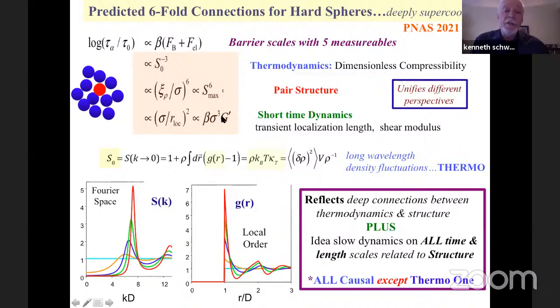And the theory predicts the barrier scales with 2 short-time dynamical properties, which are predicted by the theory: the localization length, which is the minimum of the dynamic free energy, and the dynamic shear modulus. So this provides, I think, a unified perspective in the sense that it's just one theory, but all these things are consistent with the ideas of it. Some of these reflect deep connections between thermodynamics and structure, such as the first one, and the other reflects the idea, which is really also the mode coupling idea, that slow dynamics on all time and length scales is related to structure.